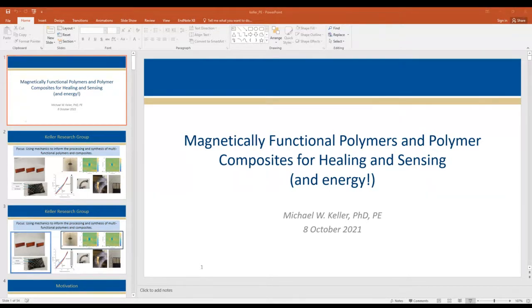But once we got that done, we were able to demonstrate some damage detection. This is a thin material. We scratched it, and you can see those nanoparticles form along that scratch. So we were able to take the two nanoparticle species, put them in there, scratch it, and demonstrate that damage detection occurs. We tried to do some damage detection in some TDCBs. Unfortunately, in these two cases, we could never generate enough material to be magnetically detectable. That was sad.